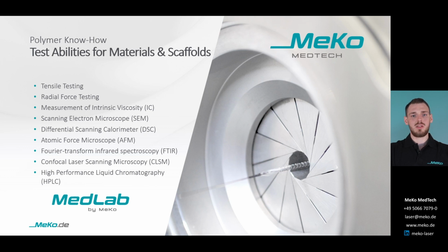Besides those mechanical analyzers, the MeKo MedLab has many testing capabilities for the material itself, like DSC measurement or the measurement of the intrinsic viscosity, which gives an indication of the polymer chain length. And this, for example, is used to show that the laser cutting does not impact the material in a bad manner. As you may already know, MeKo also offers a service of scaffold coating with and without integrated drugs for R&D projects. The coating thickness is, for example, tested with confocal laser scanning microscopy, while the concentration of drugs in the coating is evaluated using high-performance liquid chromatography.